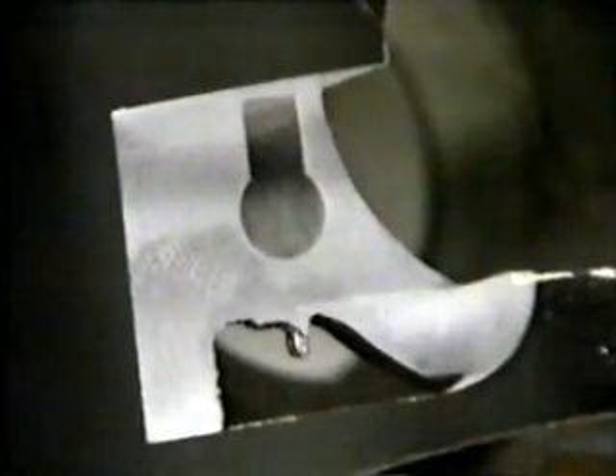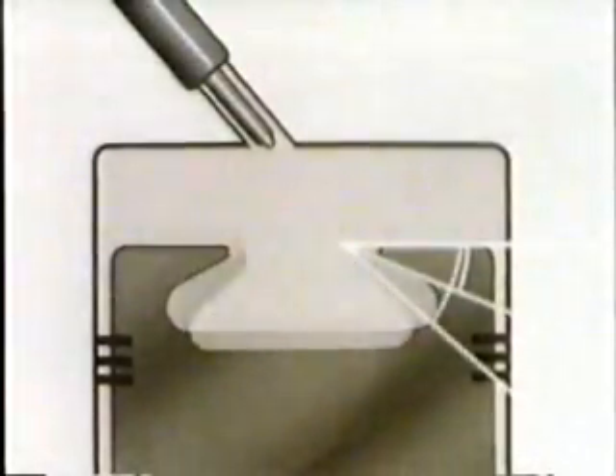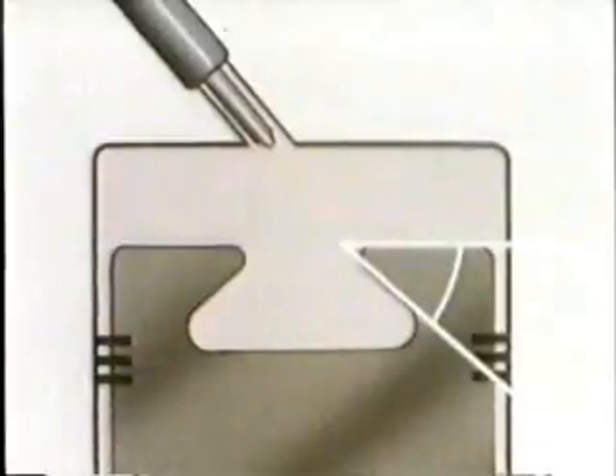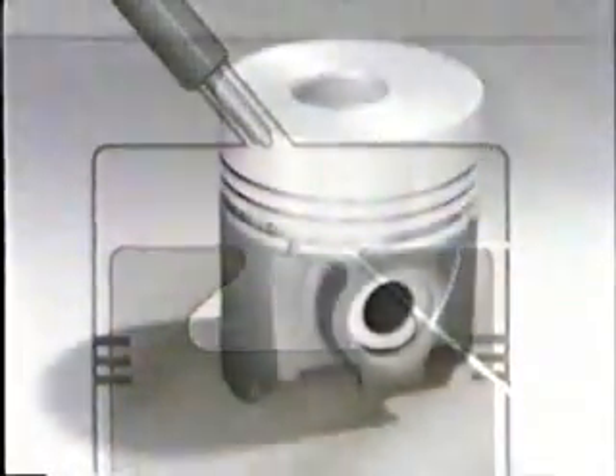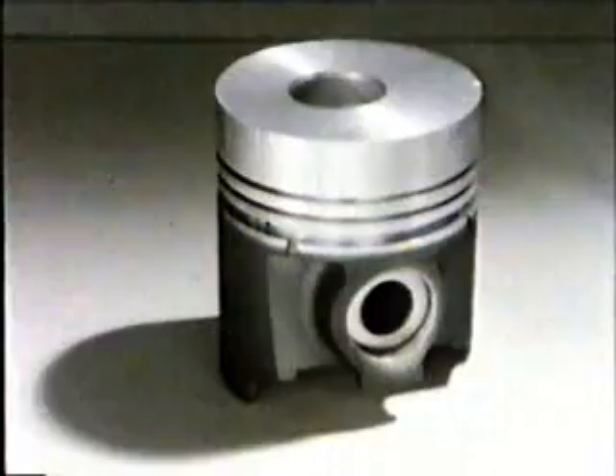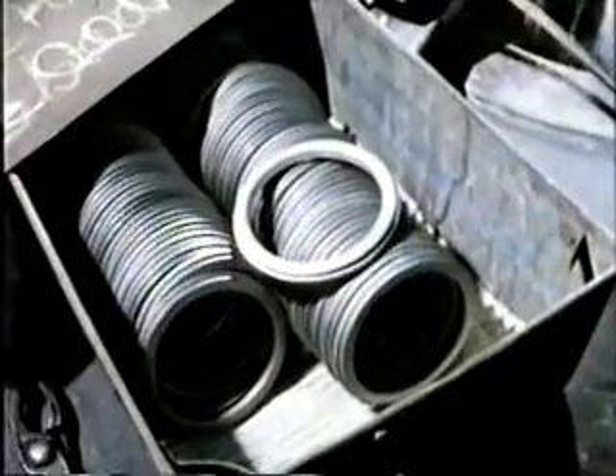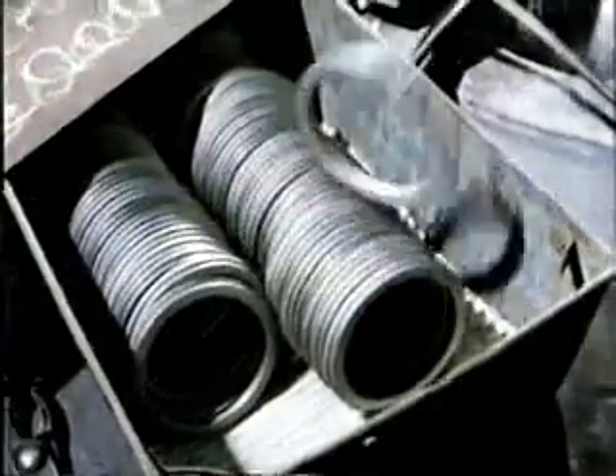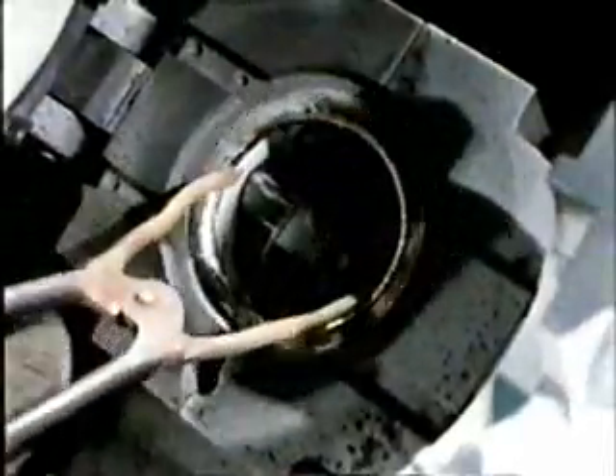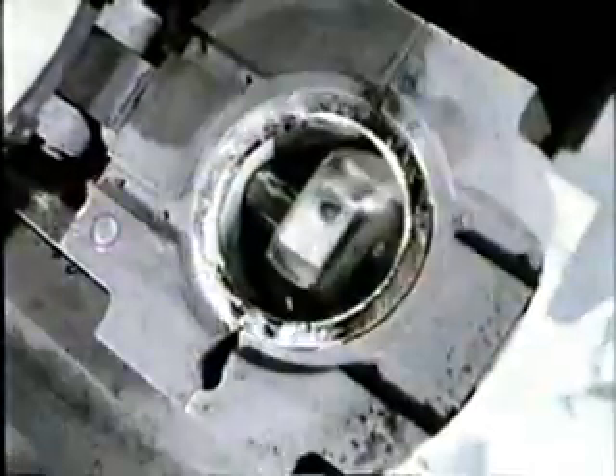Eventually a compromise was reached. The angle of the lip was increased so that the piston could be made in a single aluminium casting. The piston is die cast. First, a cast iron ring is dipped in melted aluminium. The aluminium coats the ring and also raises its temperature, enabling it to form a better bond with the casting. The ring provides a strong seating for the piston rings. It's placed in the die, which is then closed.